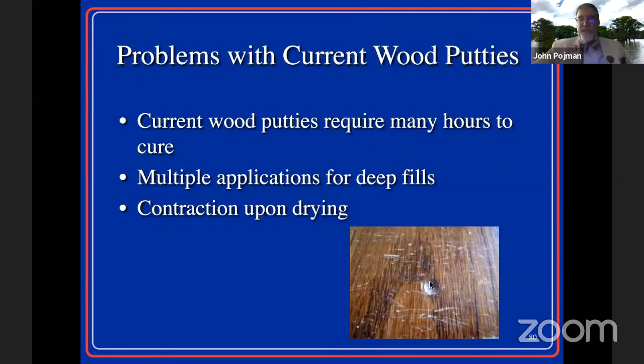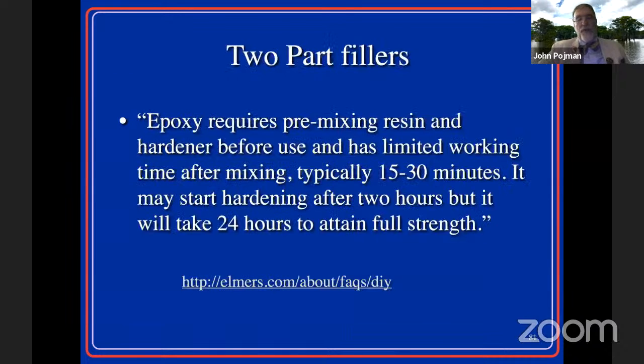So this is one problem with some of these. When you have a little hole that you want to repair in the wood, some systems shrink when they harden, so you're not left with a uniform surface. Another way people do it is with epoxies. Some of these you have to mix. You have about 15 minutes to work, and they still take about 24 hours to get full strength.